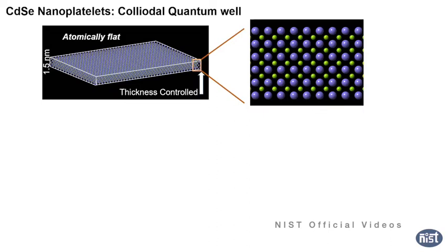Mainly I worked on the platelets, the quantum well systems, as I told you very earlier. When it goes to 2D, one-dimensional confinement, it's called quantum wells. It's cadmium selenide platelets, and you can see very nicely it's a rectangular plate, and this one direction is very confined, only 1.5 nanometer thickness, only 5 atomic layers. This is cadmium, this is selenium, only 5 layers, and you can very highly distinguish the cadmium selenide.